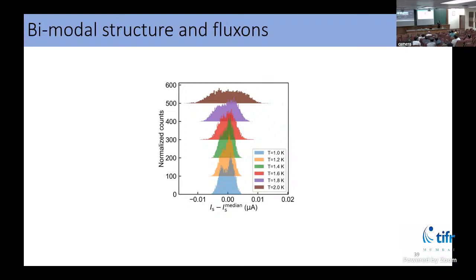And even so, when I keep on increasing the temperature, there are many, many vortices that keep on popping in the network. Then basically you have a very wide distribution where different strengths of vortices are making different networks turn or switch at different currents. So you have a distribution that is much, much wider. So basically it becomes multimodal. Now you cannot actually see each mode separately because it's sort of proliferated.